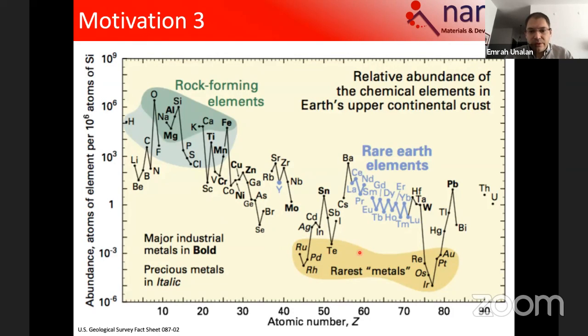And we all know, I believe, that indium is getting scarce. One might say that silver is right next by. It is true, but 100 milligrams of silver nanowires can coat a meter square of area. So it is, in that regard, very cheap compared to indium. But if you followed the recent metal prices, for sure gold increased a lot in the last couple of months, I should say. Silver is also increasing crazily, but even still, copper is, very roughly, 2 orders of magnitude cheaper than silver in bulk form.